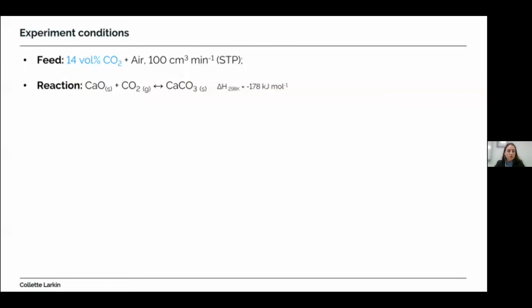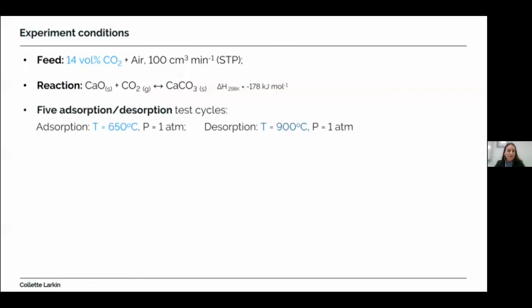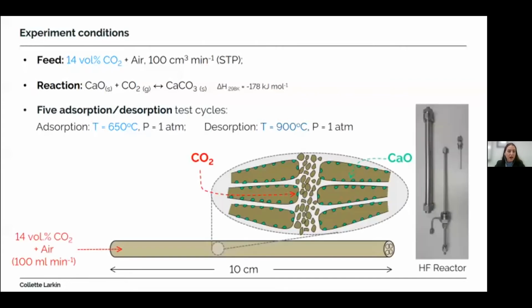And to produce stabilized results, 5 adsorption-desorption test cycles were completed for each adsorption unit, and adsorption and desorption temperatures of 650 degrees Celsius and 900 degrees Celsius were selected in accordance with literature. And I've included a schematic here to show how the feed flows through the hollow fibre adsorption unit and how the CO2 diffused into the fingers where it contacts the calcium oxide. And on the right-hand side, you can also see a photo of the hollow fibre reactor where we place the hollow fibre adsorption unit inside.